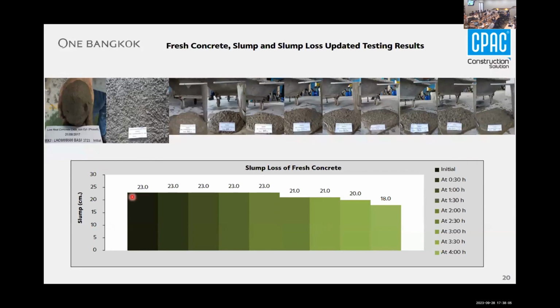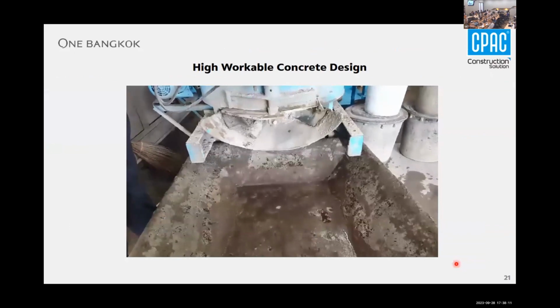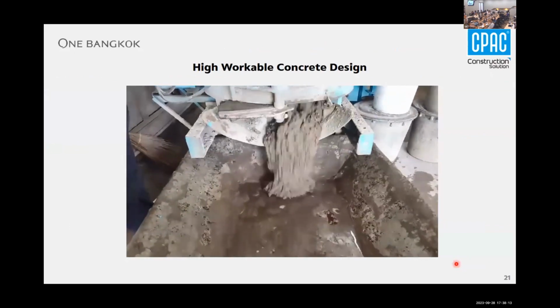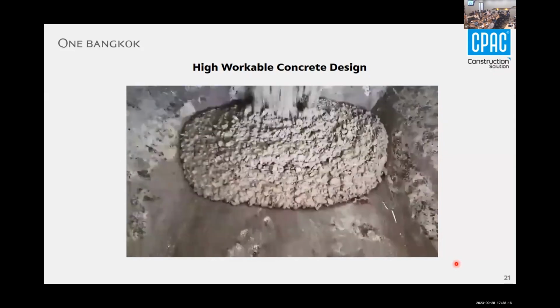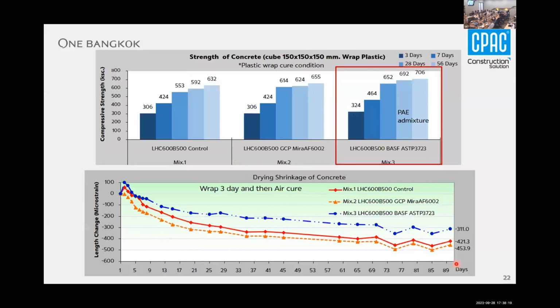And you can see here the slump retention at 4 hours. And this is our lab test after we do, you can have a look at this. We get the strength around 56 to 70 MPa. This one is in cube, but we can convert it to around 65 or something like that. This is in our lab, and we try to shrink it as well. And we select the proper admixture to be used for the project.